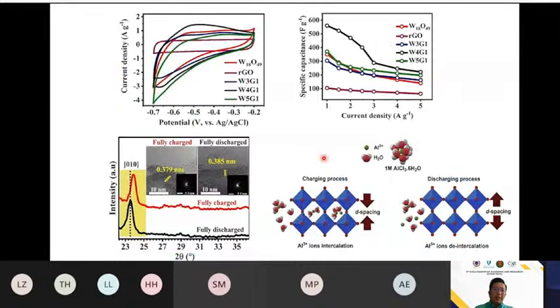We also run through the cyclic voltammetry to check it. If you look at the graph over here, it's proven that with a higher percentage of this graphene, we can achieve a higher charge and specific capacitance. And the same thing, we run through the in situ XRD to prove that the aluminum ion really gets trapped inside the crystal structure of this tungsten oxide.